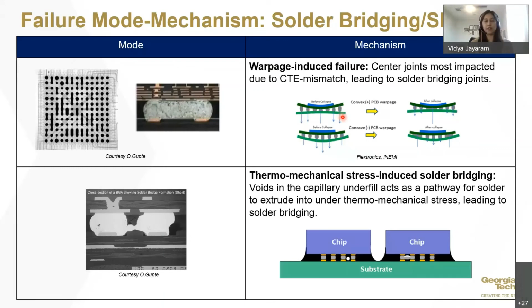So the same type of failures can happen at chip level, and they could be a different mechanism or of a different intensity. For example, if you didn't have good alignment while doing your chip level assembly, since the pitches are so much tighter, you could easily have a misalignment that could lead to missing solder or missing bump connection or bridging, things like that. So what's important is to understand, if this is my failure mode, what are the different mechanisms that it could be caused by? And that would also be related to what kind of process steps we have at chip level versus board level.